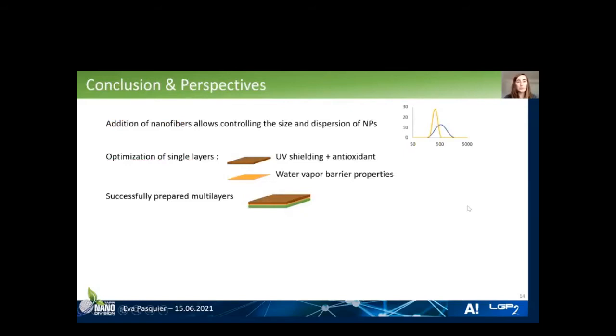So to conclude, we have prepared different nanoparticle suspensions with and without the addition of nanofibers, and we looked at the differences in morphology and also size distribution. We also prepared some single layers first of lignin particles and chitin nanofibers, to look at the UV shielding and antioxidant properties. Then we prepared this wax-based layer that showed really high water vapor barrier properties. And finally, we prepared this multi-layer.